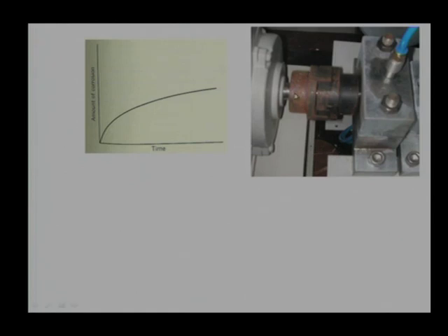The same thing applies here. If I rub this surface, corrosion will happen again, but if I do not rub and keep it as it is, nothing is going to increase. The corrosive layer will not increase beyond a certain limit, unless excess vibration dislodges it or removes it from the surface. Of course, as the layer grows, since the layer is already brittle and porous, the strength of the layer will continuously decrease. We say that the strength of this layer is a function of thickness. With increase in thickness, strength is going to decrease. So we need to be careful about that. It should not happen that the layer continuously increases and generates a number of particles.